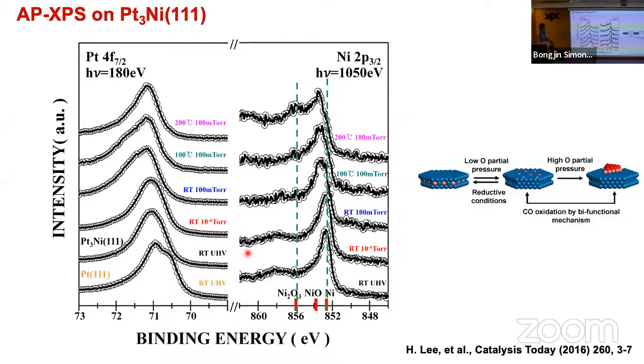Before I was meeting them, I was actually also able to run this experiment. So platinum-3 nickel, if you sputter anneal a very clean surface, you will be able to have this very nice platinum 4f metallic state. And this is the platinum 111 single crystal. So if you compare this, having nickel alloy, this is the surface state that many people may know. This surface state is actually a little bit reduced, but you can see this clean, nice metallic state when you prepare the single crystal. Once you start to introduce a small amount of oxygen, 10⁻⁶, 100 millitorr, you start to see the shoulders coming up. If you measure the nickel around the same time, the nickel metallic state now starts to move towards the left. And then you can start to see the forming of nickel oxide on the surface.